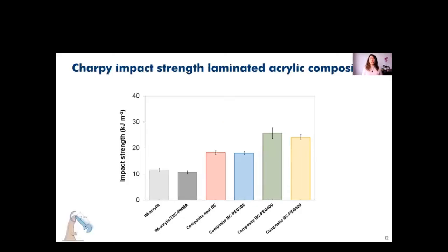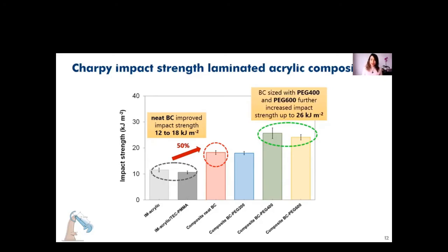And if we move forward to the Charpy impact strength properties of the composites, we will look first at the neat acrylic and the acrylic with the PMMA interlayer. They have really similar impact strength, around 11.5 kilojoules per square meter, and this value was increased to 18 kilojoules per square meter when we add BC. This means a 50% increase in the impact resistance of the already impact modified acrylic. So what happens when we add PEG400 and PEG600? There is a further increase of this value to 26 kilojoules per square meter.